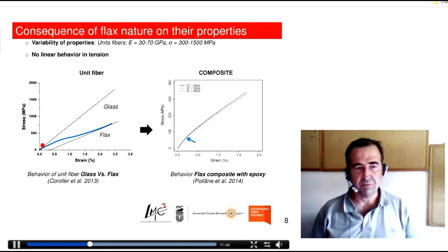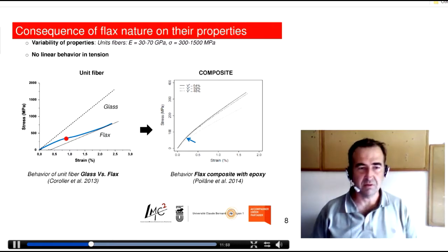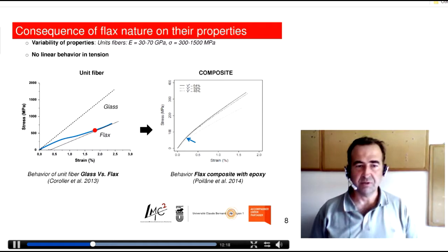For example, if we compare to glass fibers, stress-strain curves are not linear. They are mainly bilinear. First stage where the fibers rearrange themselves with a higher Young modulus, and then the second stage where the Young modulus is more or less constant. So for the next, all the properties are given in this second stage, where the mechanical properties are nearly constant.